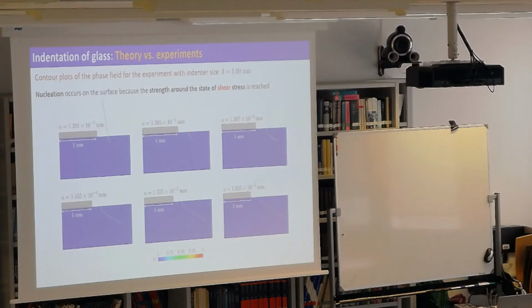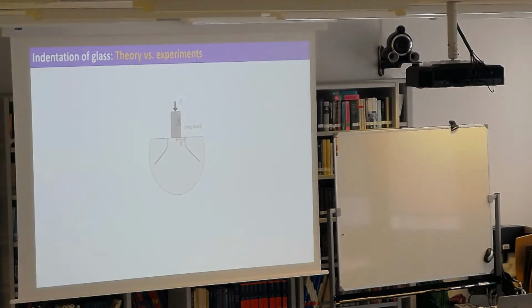So that's why I said before, if you have, not a Drucker-Prager, but any other thing that has the right shear, then you're in business. You will nucleate properly. And after you nucleate, Griffith takes over. Francfort and Marigo. Okay? And then you can compare with experiments, and it looks good, right? I mean, of course, the experiments have quite a bit of scatter.